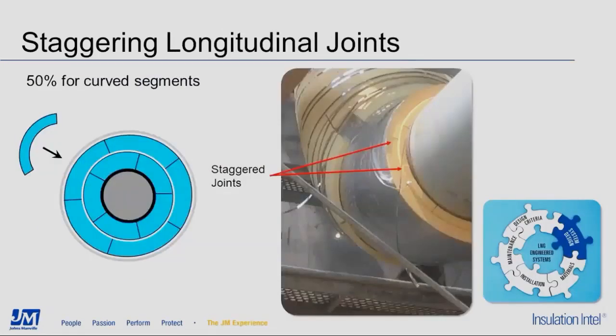Here's a drawing and a picture of the staggering of both butt and longitudinal joints when curved segments are used. On very large diameter pipe, you can't use insulation half shells, so you use curved segments, as is shown here. In both pictures, you can see the staggering of the longitudinal joints by about 50% the circumference of the curved segment. In the right-hand picture, you can see that the inner and outer layer also have their butt joints staggered.